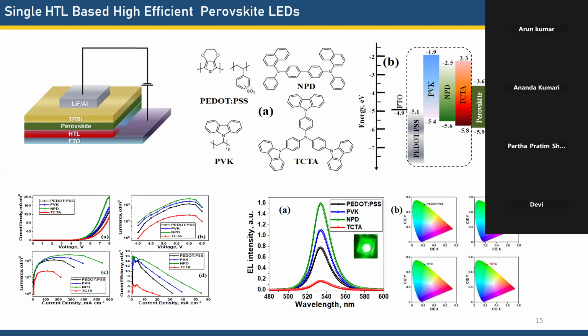Here, FTO, this is our lab work. We published it recently. FTO is fluorine-doped tin oxide, like ITO, simply. The bottom one is the glass, and the hole transporting layer is PEDOT:PSS, and we compared three different parameters. In the comparison study, we looked at how the modulation of the carrier injection happens towards the hole side. On top of that, for the perovskite material, we simply mix methyl ammonium bromide and lead bromide, and we make that precursor inside the inert gas in the glovebox. Then with spin coating, we keep a nice 90 nanometer thin film.